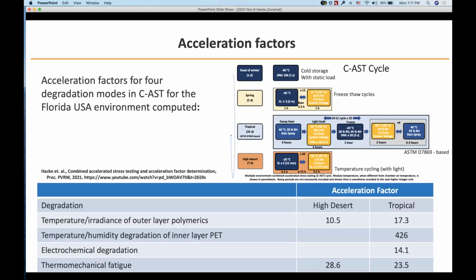A little bit more about the acceleration factors. We published this in the 2021 PVRW, but we're going through a winter, which simulates cold storage. We go through a spring with freeze-thaw cycles. We go through a tropical sequence, which is based on ASTM D7869, which finds failures in paints and coatings. And we do a temperature cycling with light test called high desert.